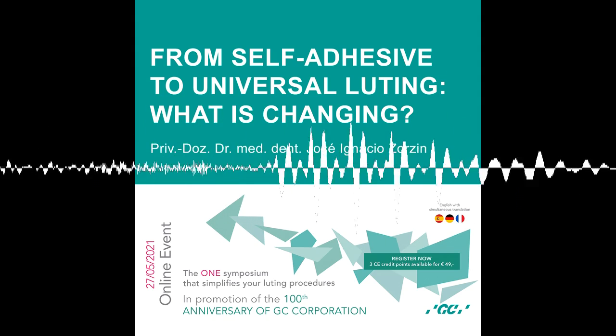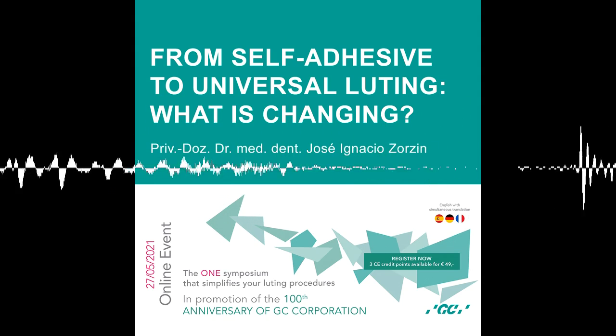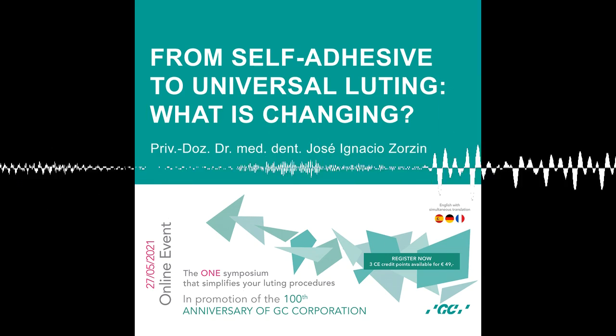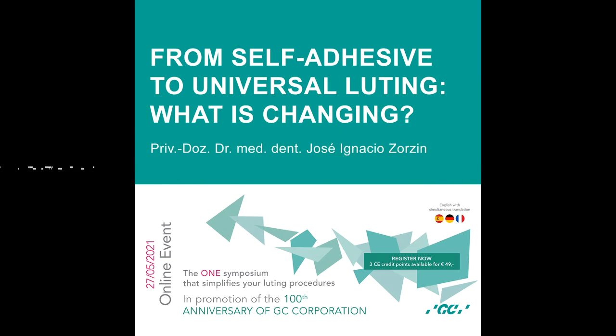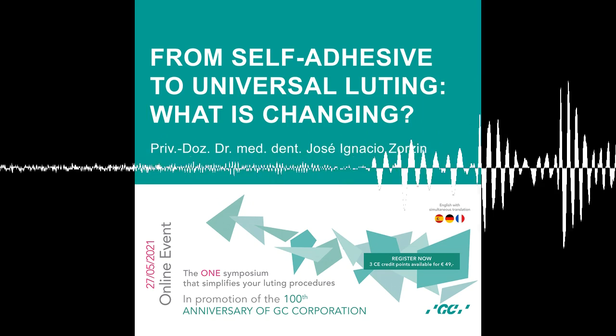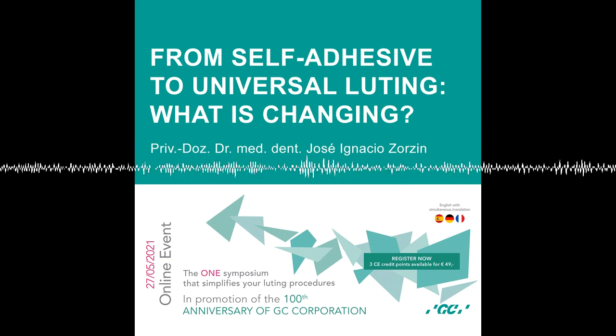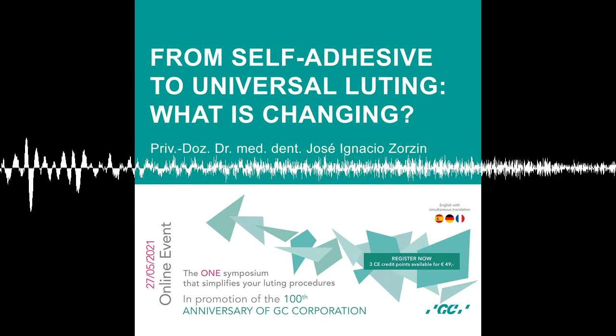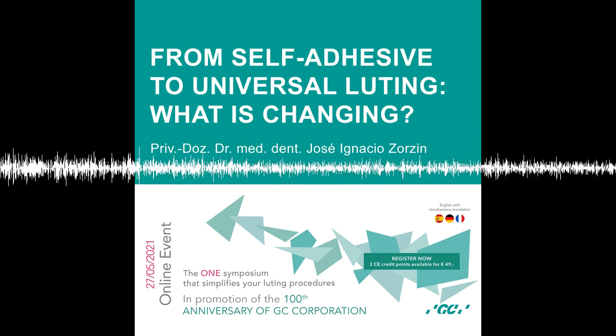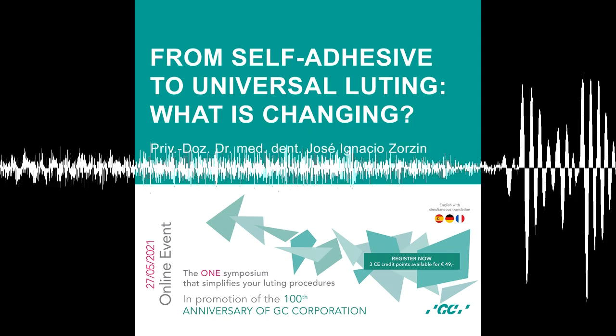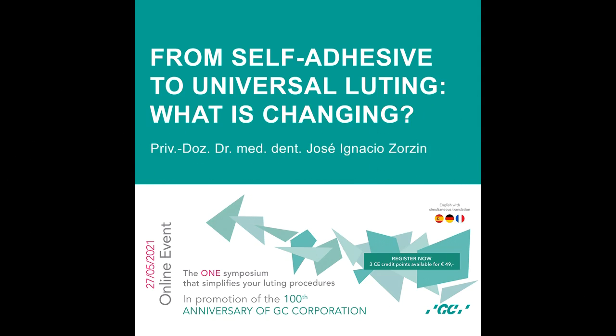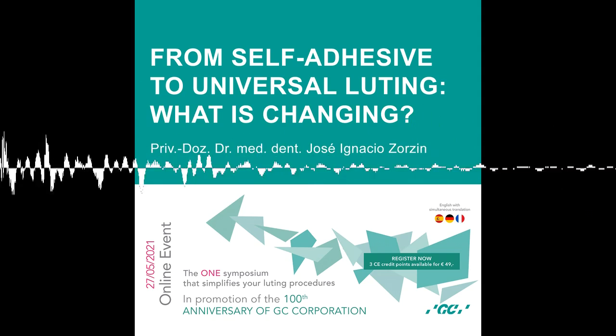I, for example, prefer to do the abrasion of restorations by myself, so I have the control after doing the try-in. Then for glass ceramics, etching with hydrofluoric acid, afterwards it's clean, really. And if you don't have those possibilities, you have to use special cleaners for that. But it's something always to keep in mind: clean substrates on the tooth side and also on the restoration side. Actually, I also etch everything personally.